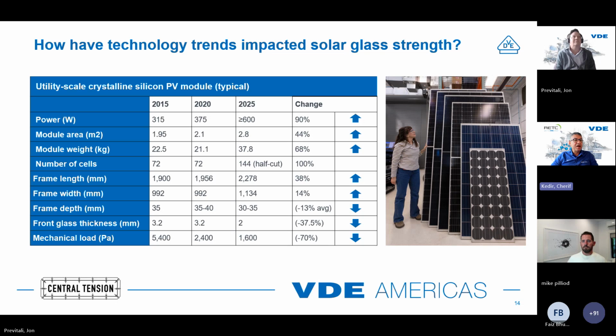There was a need to have light enter the module from the backside. There are two ways of doing it. You can either add a clear backsheet or you can add a clear piece of glass. Taking a module that was getting larger and larger with a 3.2 millimeter front glass, adding another piece of glass to the back was just too heavy to deal with. And so manufacturers responded to a lot of criticism from EPCs and developers, and they introduced modules with thinner glass.